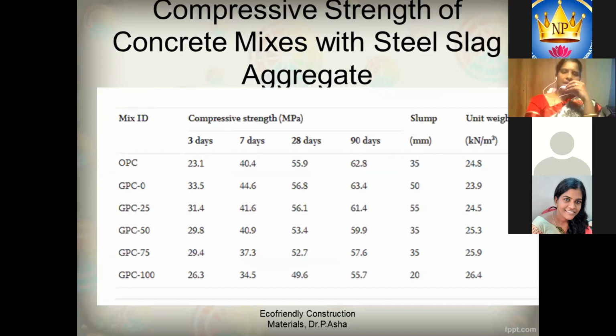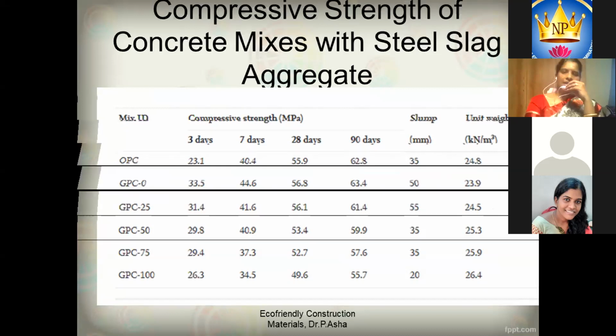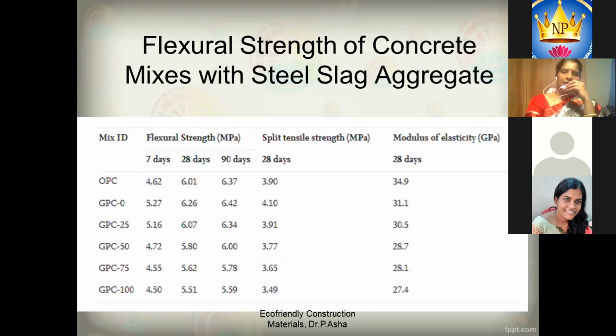If you take the unit weight, it is nothing but the density of concrete. So 24.8 is the conventional concrete unit weight, whereas for geopolymer concrete with steel slag, the unit weight keeps on increasing. What would be the reason? The density of the aggregate is higher. That is mainly causing the increase in the unit weight. So like this, we have to analyze the effect. Similarly, for the flexural strength and split tensile strength, all these parameters, the steel slag aggregates show properties comparable to the conventional concrete with the 25% replacement.